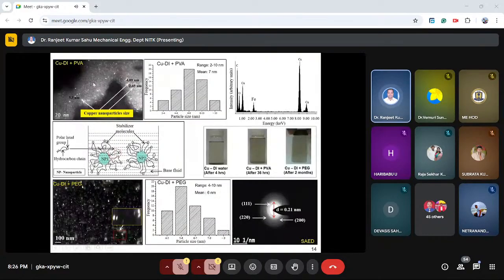Polyvinyl alcohol, PVA, exhibits exemplary characteristics: it is non-ionic and water soluble. It has strong film forming quality and wetting effect. When this polyvinyl alcohol is added to the DI water at a concentration of 1 weight per volume percentage, the experiments were conducted under similar input conditions. This is the TEM image of the copper particles dispersed in this PVA solution. Each bright crystalline particle shown here in this image represents the copper nanoparticles of size in the range of 2 to 10 nanometer with a mean size of 7 nanometer.